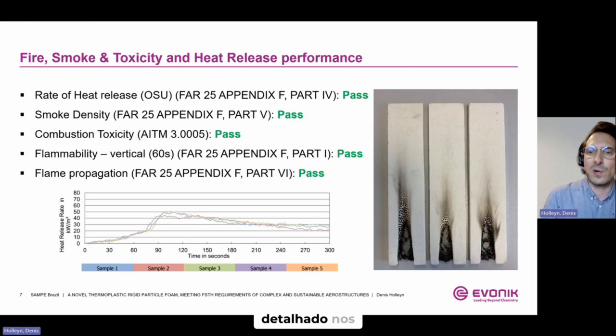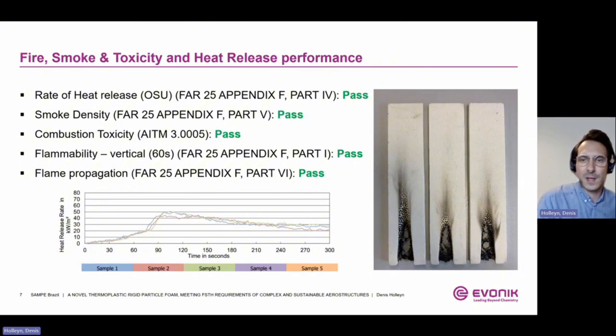Let us have a detailed look at the typical and challenging FST and heat release requirements of the aircraft interiors industry. The listed test standards are the widely applied test standards for interior components. With raw foam, we can easily pass all of those requirements and exceed the limit as specified in the test standard. Exemplary for this, you can see the test specimen after testing for the 60-second vertical burn test, and I also included a diagram presenting the results of a rate of heat release test on the left-hand side. As you can see, all values stay well below the requirements of 65 kilowatts per square meter. Therefore, the test was passed.